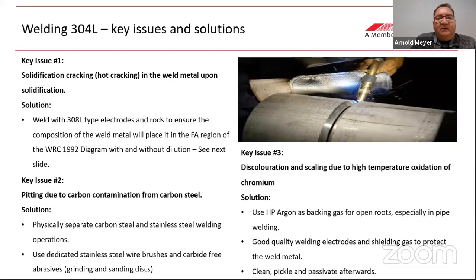The 308L type electrode places it into a region where upon cooling you will form a small percentage of ferrite first. That's called primary ferrite or delta ferrite, and this then sits on the austenite grain boundaries, and it prevents the low melting phases from migrating to the grain boundaries, and by that mechanism prevents the hot cracking.